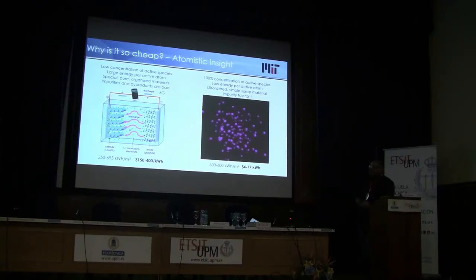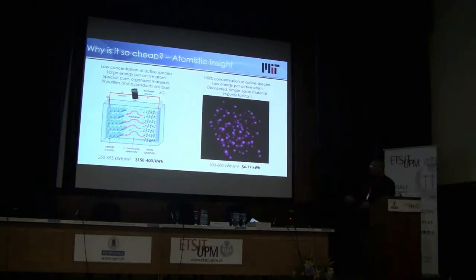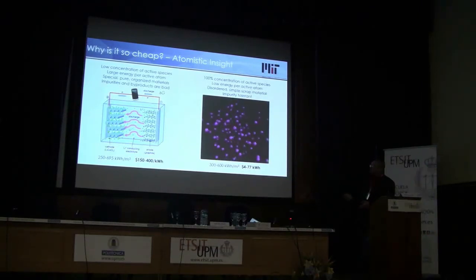And as a result of this, you can end up with high energy densities because there's a lot of energy per atom that's participating. But the costs can be high and the lifetimes can be low because they're rather sensitive to deviations from this structure. So if the battery heats up or if it gets side reactions, these kinds of things can damage it. And so it's not particularly robust from a very intrinsic perspective, just the way that it's set up.